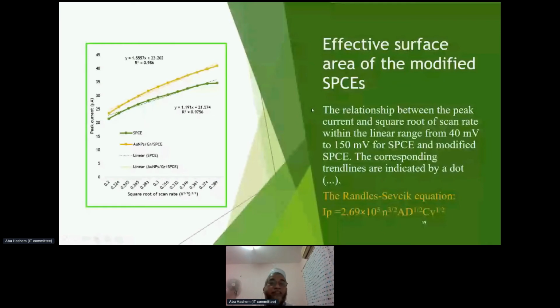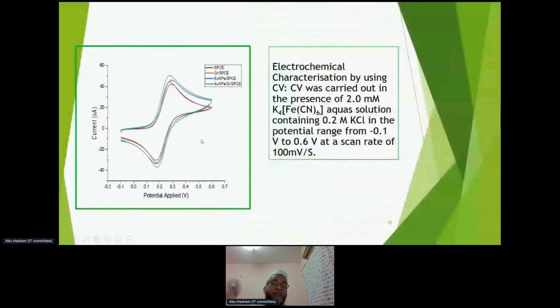After modification, we characterize the electrode. This is indicating the modified electrode activity, which is determined by the Randles-Sevcik equation. We characterize the electrode electrochemically by CV. The highest peak is for the gold graphene modified species.